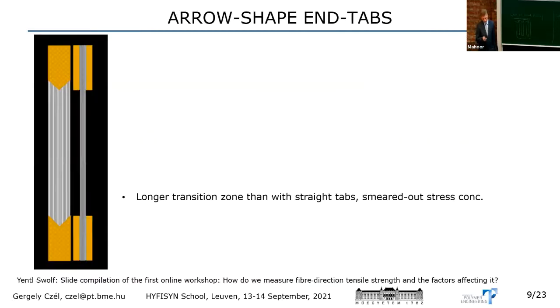Then we can use special arrow-shaped end tabs, which are not cut perpendicular to the side of the specimen, but under given angles. And actually this angle is a parameter of this tab geometry. And the key idea here is to have a longer edge along which the stress concentrations arise. So in a way, we can extend, or we can make the affected area larger by applying these arrow-shaped end tabs, and we can smear out the stress concentrations over a slightly larger area.